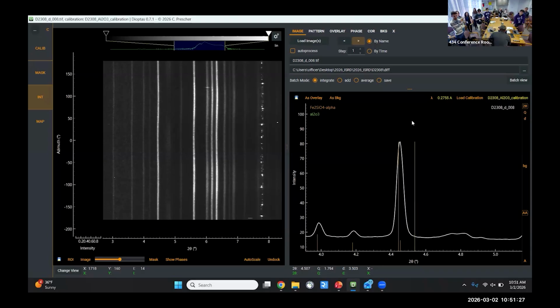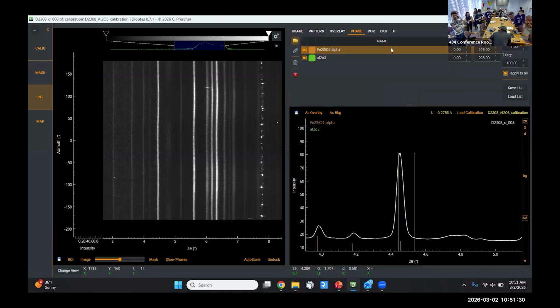And we can measure what the pressure is if we know the equation of state, which is something that relates pressure, temperature, and volume. So if we increase this, we're still at room temperature. So this is at 0.7 GPa. So we can measure the pressure directly in situ using the synchrotron.